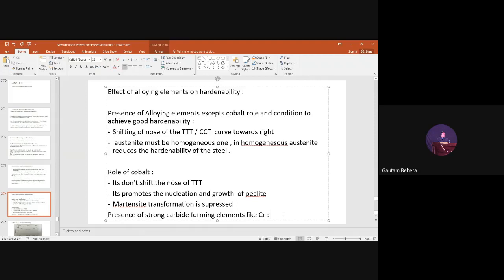Cementite or iron carbide is easily soluble above 650 or so, but to dissolve other carbides like chromium carbides, or vanadium, niobium, it requires very high temperature. Or once it is soluble, it takes more time to get homogenized also. So the presence of strong carbide forming elements like chromium suppresses the hardenability, or makes the hardenability poor. So, poor hardenability.